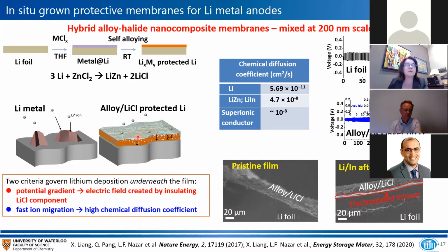And if we didn't drive deposition under the film, the lithium would simply deposit on the top and we wouldn't be any further ahead. So these are the two important points, the electronic resistivity of the film and the fact that these films have a very high chemical diffusion coefficient for lithium. And so we can see stripping plating over 700 cycles, which is with low polarization, which is reasonably stable, whereas just on foil, we start to see microdendrites forming after even 200 cycles. And this just shows the lithium that actually is plated underneath this film.